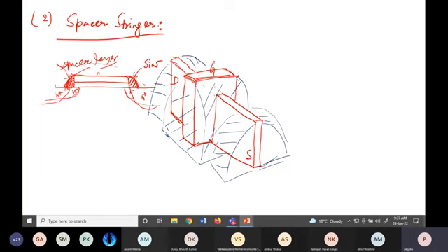Now it is good for a planar structure because it is there in the side walls around the gate, but for FinFETs, the side walls for drain and source are also vertical, so the spacer layer will be there. Now that is a problem. Why is that a problem? Because your source and drain need to be doped, right? So you need to open your source and drain so that you can implant there. So you have to remove your spacer layer at source and drain.